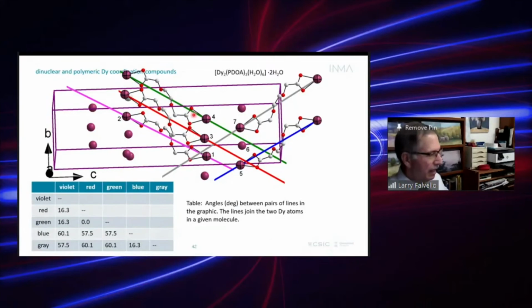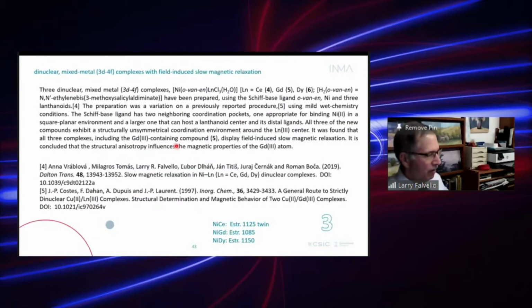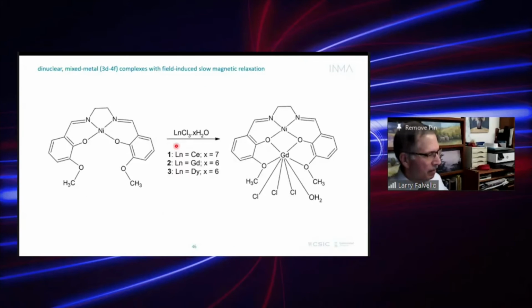Right? And the angles between pairs of these molecules are not 0 in all cases. There's a 16-degree angle between violet and red. And so right then and there, if you measure the susceptibility of a single crystal, you're getting an average of two tensors that are slightly tilted with respect to each other. Okay? We can analyze that for the third group of compounds, but basically it comes out the same.